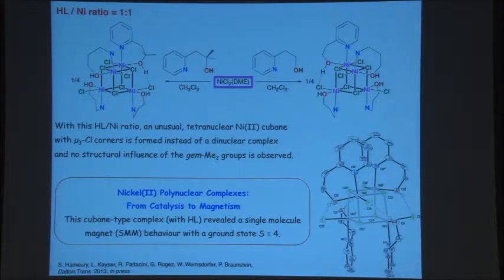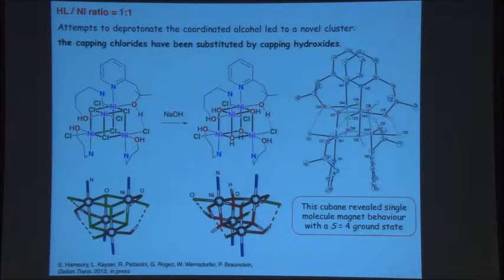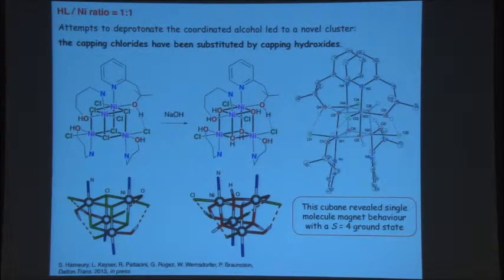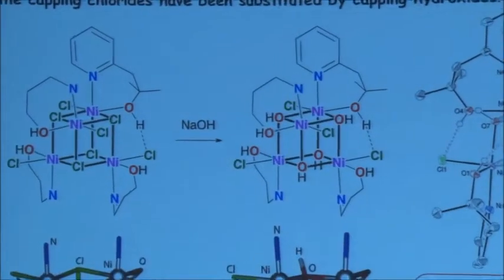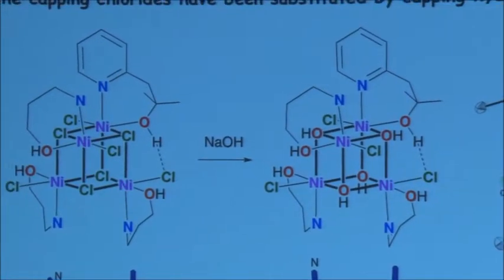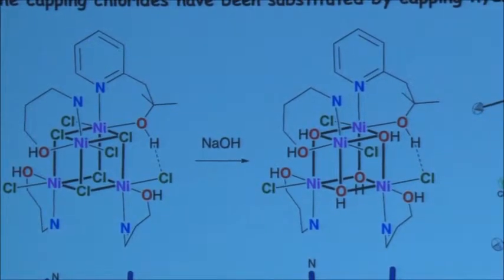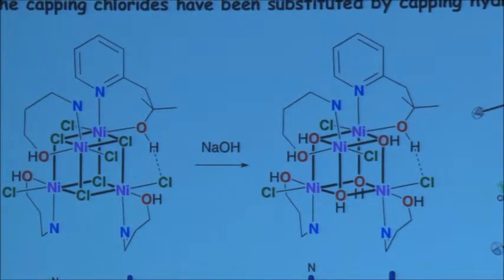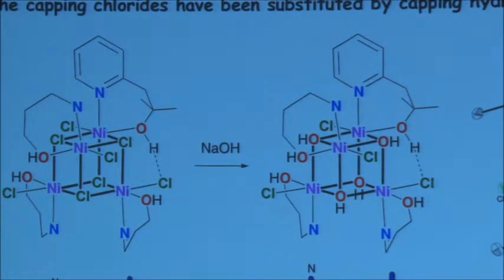So we started this project to prepare pre-catalysts for ethylene chemistry. And now we end up having compounds that have properties in molecular magnetism. So that's something which was not anticipated at the beginning of the work. So now let's continue and see what happens still with the 1-to-1 ratio. We have this alcohol function, as I mentioned before, and we thought maybe we could modify not only the electronic properties of the ligand and maybe of the catalyst, but also the solubilities, by trying to deprotonate these OH groups here.